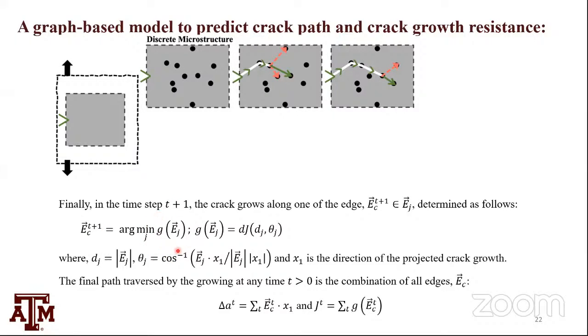And this function g is related to dj, which is the increment of crack growth resistance, which should be a function of the distance between the 2 and its angle of inclination. We'll come back to what that means. The distance is the magnitude of these vectors, and the angle is the projection of these vectors in the crack growth direction x1, straight ahead. Projected crack growth is what matters. It's going to break my specimen into 2 pieces.